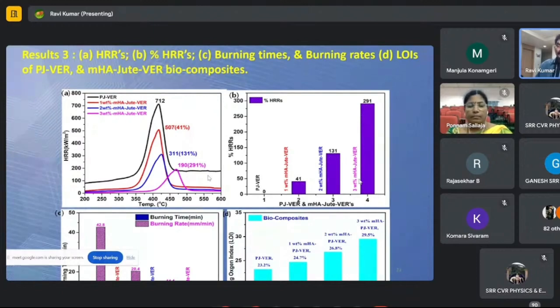It means almost 6 times higher, as you can easily calculate. And the percent HRR, compared to the PJVER, the PJVER is not showing anything, but from 1 weight% to 3 weight%, it increased from almost 0 to 291. So the same image I tabulated here graphically too. And also you can see burning time and burning rate. The burning time you can see in the blue, and the burning rate is 42.8 and 20.4, and in the case of 3 weight% it gradually increased, and the burning rate also gradually increased. And also here you can see the biocomposites of PJVER at 23.2%, and 1 weight% is showing 24.7. In the case of 3 weight%, it shows 29.5%. It means that the limiting oxygen index also gradually increased through the biocomposites made with MHA jute VER compared to the PJ VER.